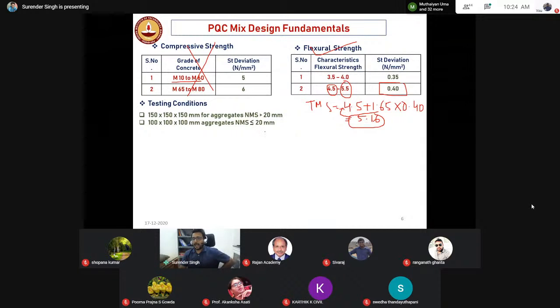Now the other thing is that I have seen many researchers and many faculties in different colleges. What they are doing is always casting 100 by 100 cubical specimens to get the strength value, or they are going with 150 by 150 mm. But they don't know the fundamentals. Why are we going for it? It depends upon the size of the aggregate. Not the maximum size. Yesterday we discussed, right? It should be the nominal maximum size. That is the largest sieve over which some of the aggregates will be retained, but not more than 10%.